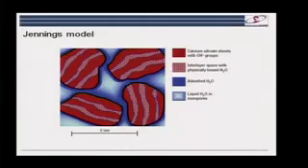Now, I'm going to spend a bit more time on this model because from the point of view of water, what is nice in this model is to see the different states of water. So here we have this idea of these little colloidal particles. Within these little colloidal particles, we have our sheets of calcium oxide and silicate, and then between these sheets we have water. So we have water in this interlayer space, which you see here is regarded as physically bound.